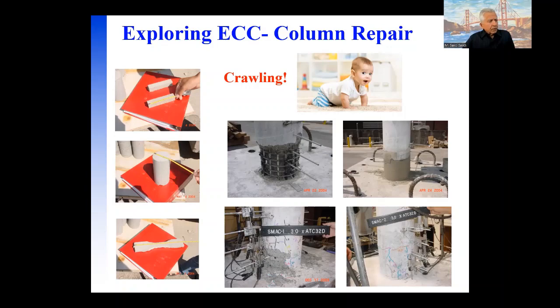So you notice that we removed the loose concrete first. In this column we had used conventional concrete. So after the earthquake testing, we removed all the loose concrete, and then we replaced that with ECC. The photo on the upper right shows a repaired column. That was the first ECC project that we used. So we retested that column after the repair, and the two pictures at the bottom show you the difference.